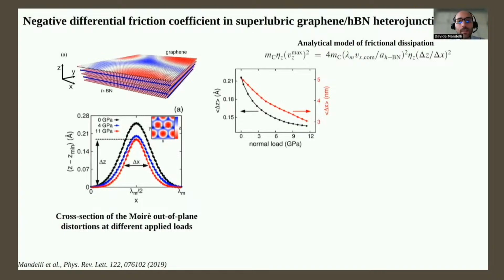And a very last curious phenomenon that we observed: this dependence on the intensity of the Moiré density wave suggests a way of controlling friction by tuning them. Given that in the case of graphene over hBN, dissipation is due to the propagation of this out-of-plane distortion, one way of controlling them, we thought, would be by applying a load that would suppress them.